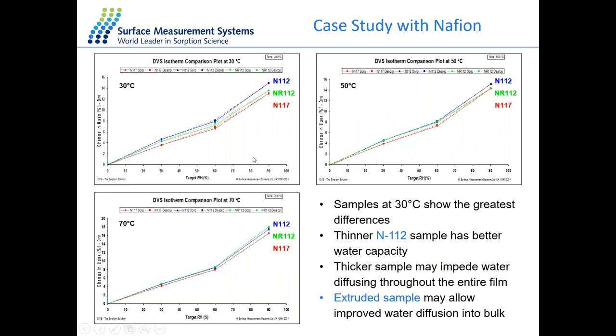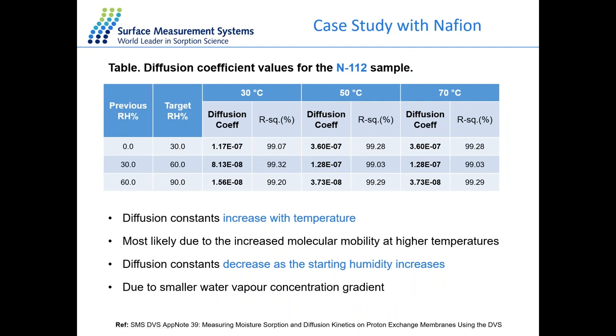And then we also calculated the diffusion constant for the N112 sample at different temperatures. So within the same line, for different temperatures, the higher the temperature, the larger the diffusion constant, which is also due to the increased molecular mobility within the sample at higher temperature.